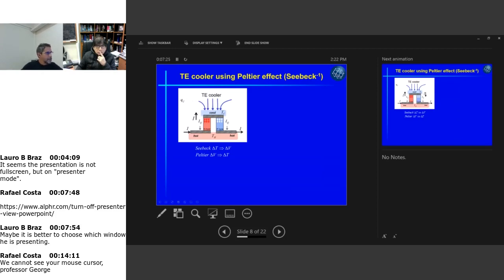So if you apply a difference of potential here to create a current, so you are driving the charge current from the outside, you see that the positive charges are going to go this way, therefore the electrons here are going to come this way, and the holes are going to come this way, but they are not only bringing charge with them, they are bringing energy too. So they are removing heat from the top part of the device and bringing it to the lower part of the device. So as a consequence of the current passing here, you're going to have a lower temperature here and a higher temperature here. So you have a heat flow caused by the charge current in this direction. And this is the so-called Peltier effect.